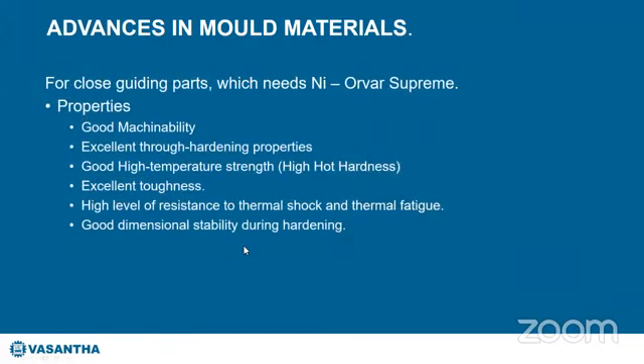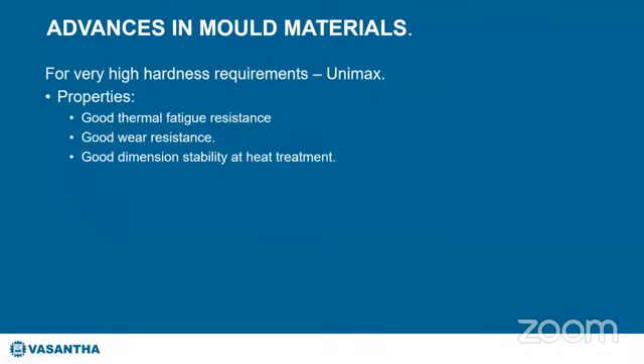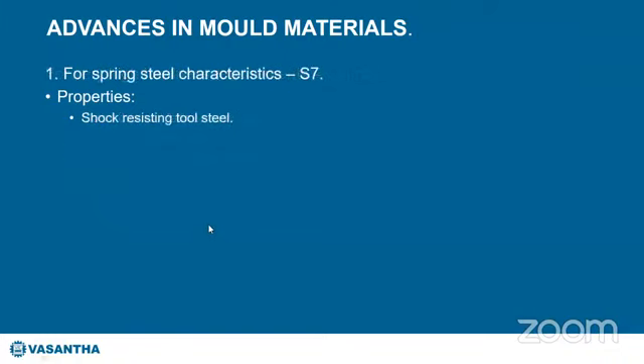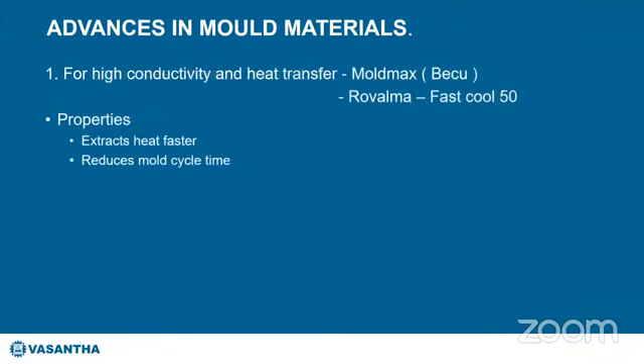Orvar Supreme is the material which we generally use for the core side of the mold, which has good machinability, excellent through-hardening properties, good high temperature strength, that is high hot hardness, excellent toughness, high resistance to thermal shock and thermal fatigue, and good dimensional stability during hardening. Unimax is the material we generally use for good thermal fatigue resistance and good wear resistance. It also has good dimensional stability at heat treatment. S7 is a spring steel material we use for shock resistance, generally used for sprung cores and lifters, where spring steel is of great help. Then for high conductive materials like beryllium copper and Rovalma Fast Cool 50, these are used where we need to extract heat faster and reduce the mold cycle time.